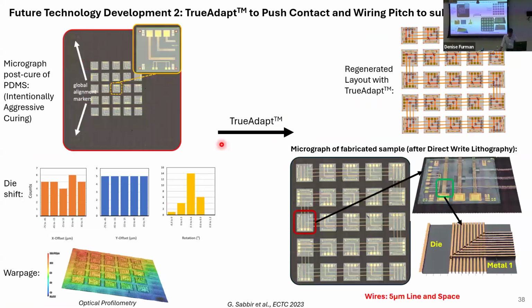So the thing is the misalignment. In this case, the misalignment was actually exaggerated, because with PDMS, the amount of misalignment the dies have during curing depends a lot on what temperature you cure at. If you cure at high temperatures, there's more misalignment, and in this case it was cured at high temperature. But usually when you cure PDMS at room temperature, over a 100 millimeter wafer from one end to the other, you have only around 6 micron misalignment.